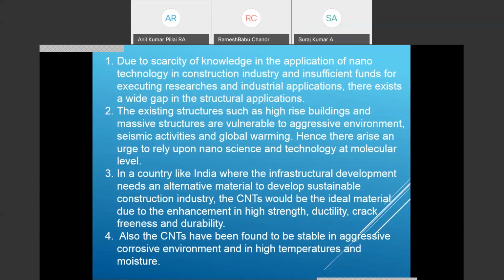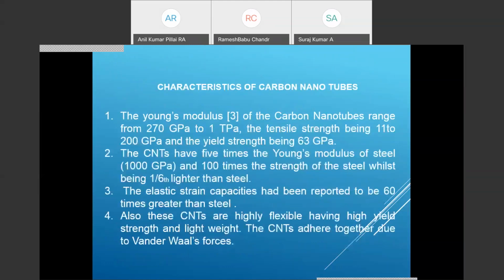CNTs would be ideal material due to enhancement in high strength, ductility, crack freeness, and durability. They also have been found to be stable in aggressive environment. Carbon nanotubes have a Young's modulus of 1 terapascal, tensile strength of 200 GPa, and yield strength of 63 GPa. The CNTs have 5 times the Young's modulus of steel, 100 times the strength of steel, while being 1/6 the weight of steel. Elastic strain is around 60 times greater than steel. Also, the CNTs are highly flexible, having high yield strength and lightweight.